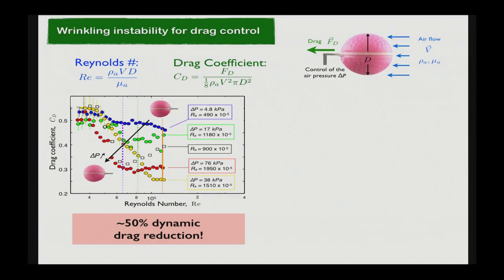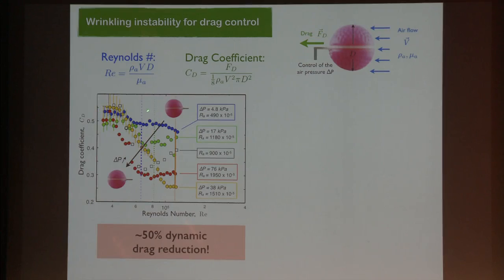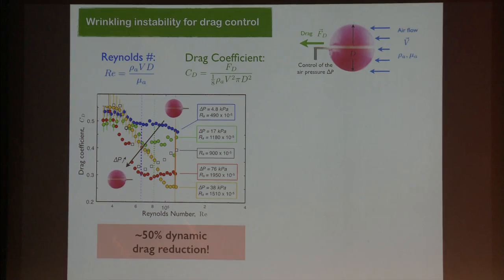And so this is a wonderful plot that tells us that for the same sample, I'm not changing samples. This is for one sample, and I'm depressurizing it. Different colors mean different states of depressurization where I'm changing the amplitude. As a function of wind speed, I can go from smooth samples with a high drag of around 0.5, which is what I had shown from the classic results from the 70s, and I can switch these structures to show a much lower drag, around 0.3 or 0.25, so nearly a factor of 2, just by depressurization. And so we can get approximately 50% dynamic drag reduction.